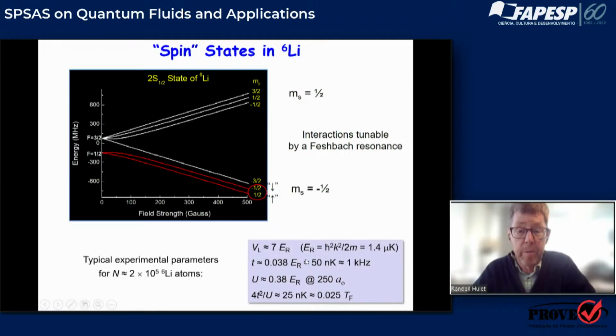So here are some typical parameters, more for the expert. There's a lattice which has a depth of 7 recoil energies. This is the definition of the recoil energy. In lithium-6, it's about 1 microkelvin. This is the tunneling coefficient, T, at that lattice depth, and it's about 50 nanokelvin in energy, or about 1 kilohertz in frequency. The interaction energy is about 1/3 of the recoil energy. So, something about 10 times bigger than the tunneling. And the super exchange as a consequence is pretty much maximized at about 25 nanokelvin at this lattice depth.